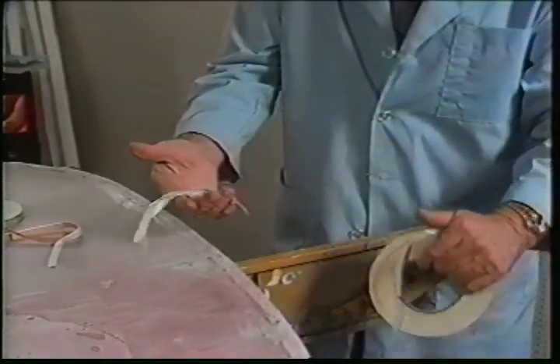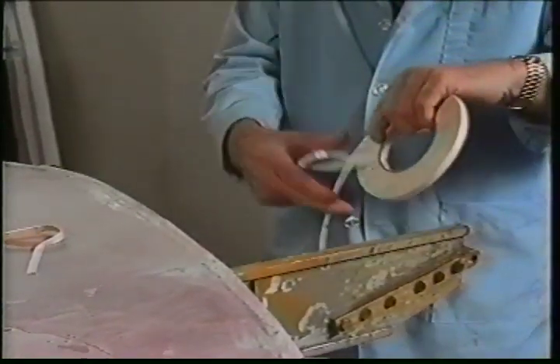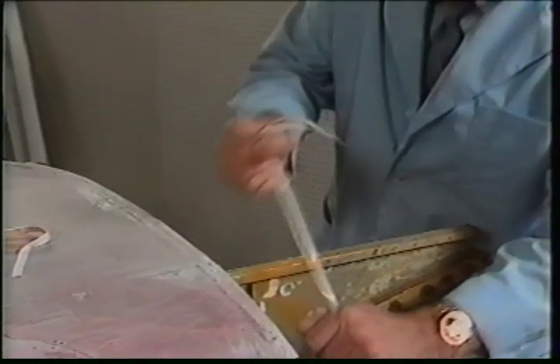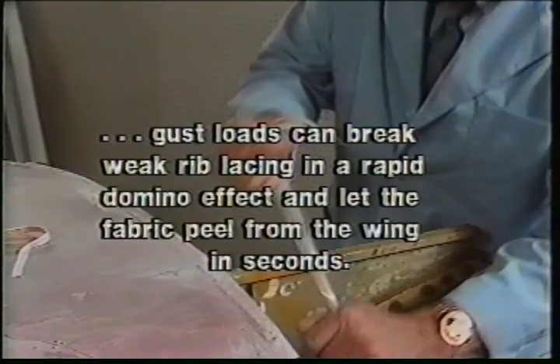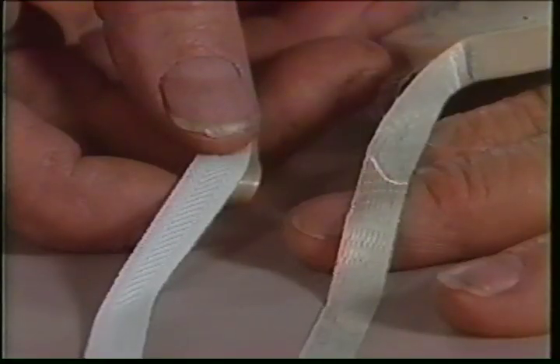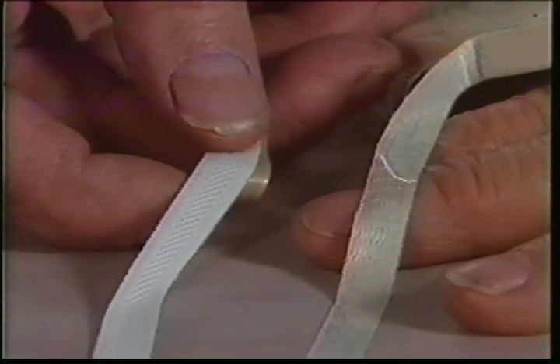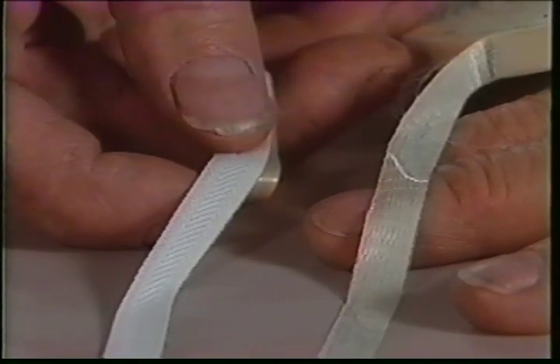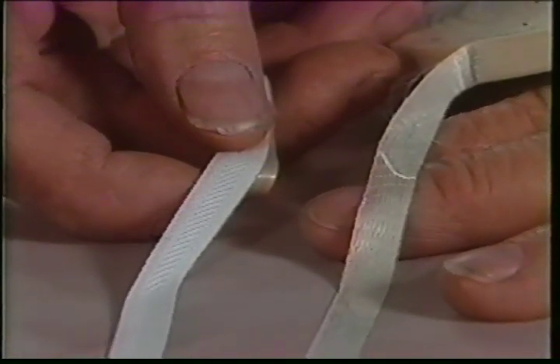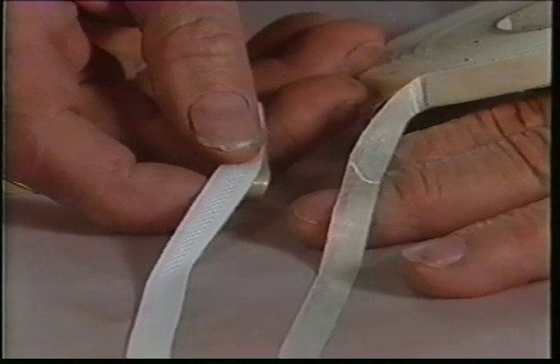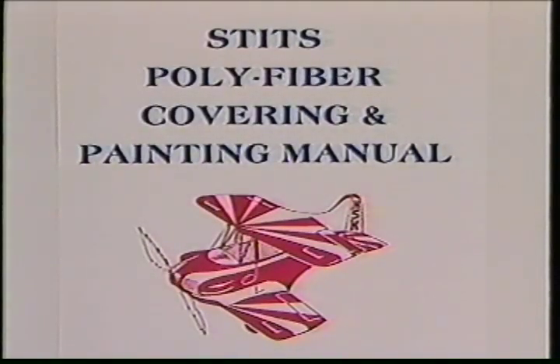Low-wing loading slow aircraft may fly for years with seemingly satisfactory results with weak rib lacing. However, when inadvertently caught in turbulent air conditions, gust loads can break weak rib lacing in a rapid domino effect and let the fabric peel from the wing in seconds. There have already been several fatal accidents caused by glass filament strapping tape shearing through and allowing the fabric to balloon and rip off the wing. The manual warns against the dangers of gluing the fabric to the ribs as a substitute for a proven mechanical attachment.